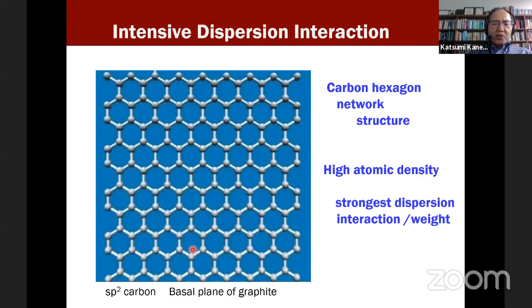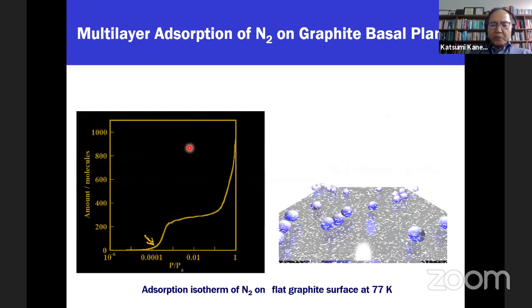In such a case, the carbon structure, the graphene structure, is very, very important because this carbon has a highly compact structure. Then this graphene structure gives the highest dispersion attractive force per weight and is also inert, so the carbon structure is a very, very nice friend for adsorption scientists. Very strong adsorption force for molecules and atoms. So carbon is very important.